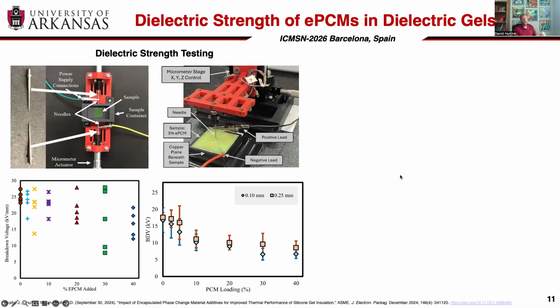But of course, as I mentioned, the high voltage isolation is the big name of the game here. These systems are often operating above 1 kV. And so you have to be able to prevent discharge or any sort of leakage event through the silicone encapsulant, not to be confused with encapsulation of our particles. But incorporation of particles into the silicone does result in reducing the breakdown voltage associated with those gels.